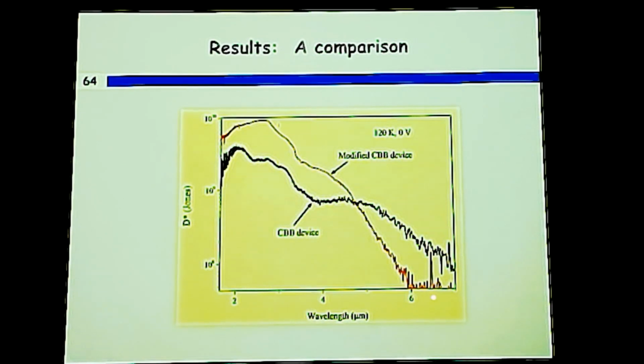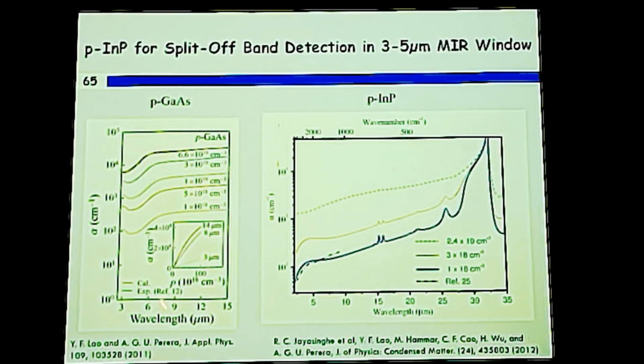Now we saw that increasing the aluminum fraction was one option. However, if we look at the spectra, the peak absorption is around 2.7 micron split-off band, and by increasing this aluminum fraction, the response in 3 to 5 becomes weaker and weaker. That is because the absorption property of the p-type gallium arsenide has an absorption dip near 3.5 micron.